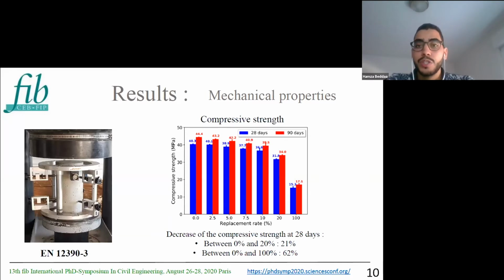So the effect of shells on the compressive strength of concrete has been the subject of several studies, and the decrease of this property has been attributed to the fragility of shells, which doesn't seem to be the case for the shells used in this study, or it was attributed to the increase of the concrete porosity. This explanation may also be the case for the total substitution, but up to 20% of substitution, the effect on the porosity of concrete is negligible, while the compressive strength decreases significantly. But the possible explanation for this decrease seems to be the weak bond between the shells and the mortar.